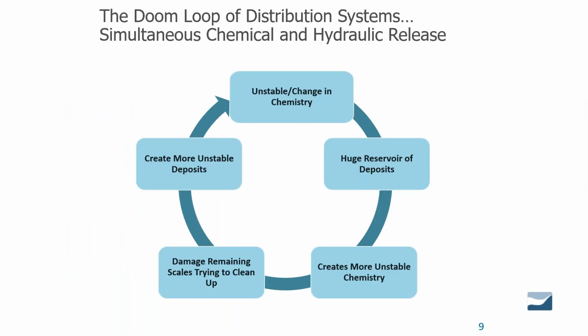Now we have a special combo release that we lovingly call the doom loop of distribution systems, when we get simultaneous chemical and hydraulic release. And this is what we see when we're in the reactive mode to these problems. We start with an unstable chemistry condition or a change in the chemistry. We apply that to our tens or hundreds of miles or thousands of miles of distribution system pipe and premise plumbing. That creates more unstable chemistry as all those pipe reactants react with the water chemistry.